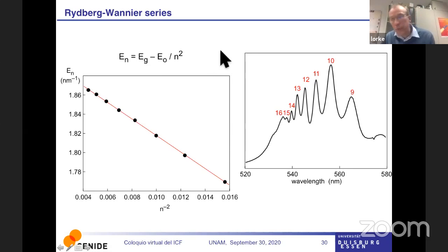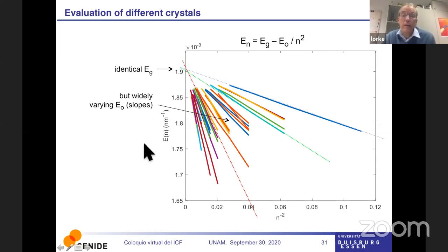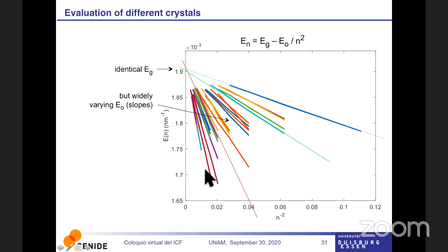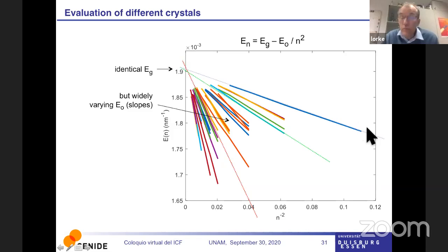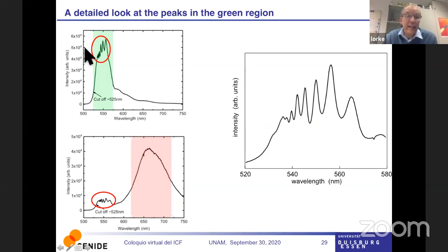Well, this may not be as convincing, but as I said, Ashwin looked at many such crystals, and each time we did the fit, we looked at how it goes against n to the -2, and we always found an n where this has wonderful straight lines. And what was really wonderful is that all these straight lines were converging at an energy, or an inverse wavelength, that was exactly where the luminescence starts.